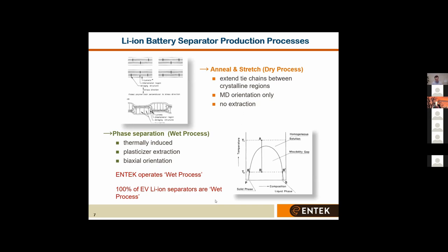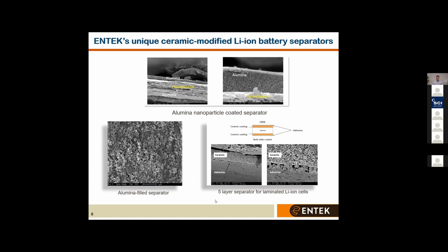The other generic process is the wet process. So it's thermally induced phase separation with plasticizer extraction. And in this case, we extract a mineral oil, followed by biaxial orientation. And what that allows is similar machine direction and cross-machine direction strength, and at thicknesses down to as low as 7 microns. So actually, today, all EV lithium-ion separators are now sourced as wet process separators. And ENTEK operates a proprietary version of a wet process separator.